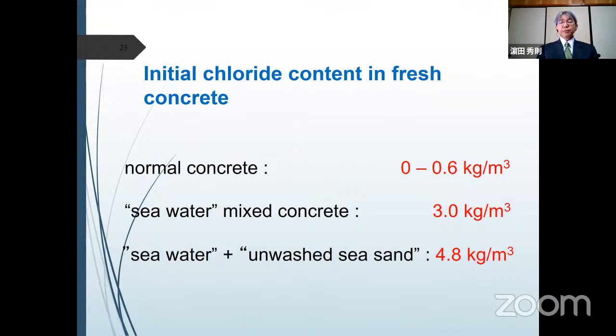Normally, if we use tap water, pure water for concrete mixing, the chloride content level is 0 to 0.6 kilograms per cubic meter. However, if we use seawater for concrete mixing, the initial chloride content level is around 3.0 kilograms per cubic meter. And if we also use unwashed sea sand for fine aggregate, then the initial chloride content level is around 4.8 kilograms per cubic meter for standard mix proportion. So the problem is the initial chloride content is quite high by mixing seawater or by using unwashed sea sand.